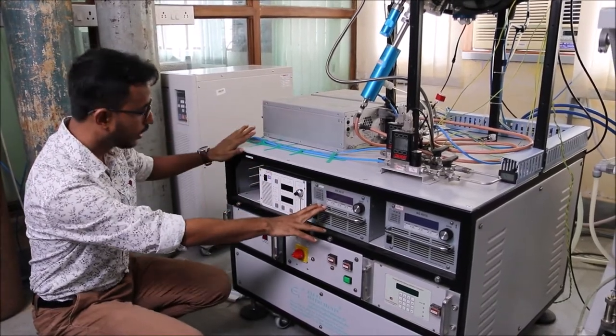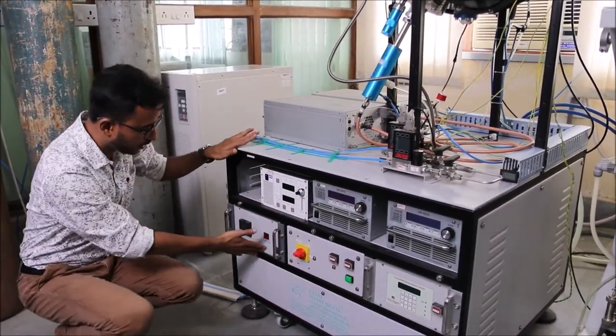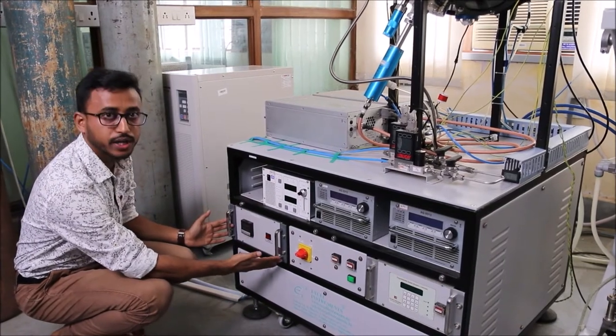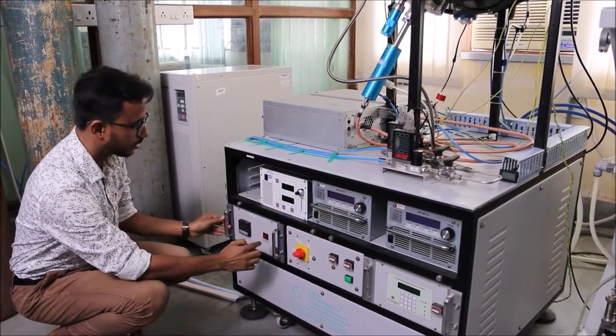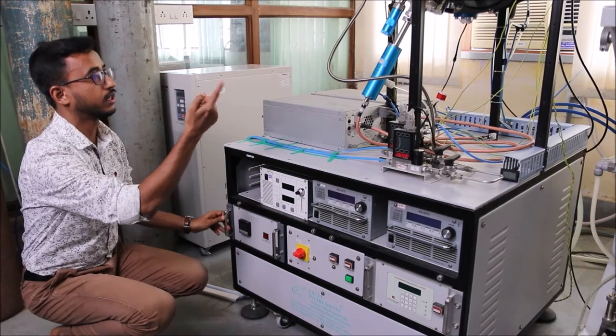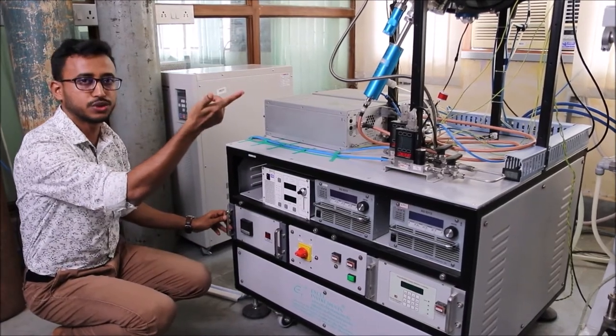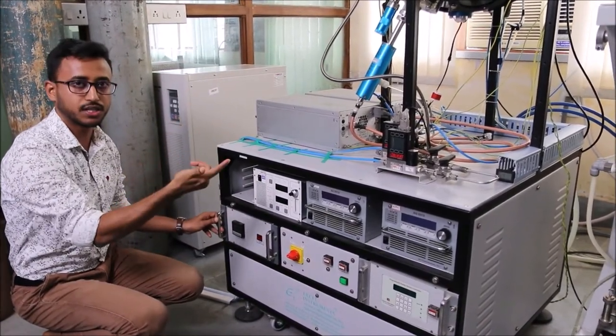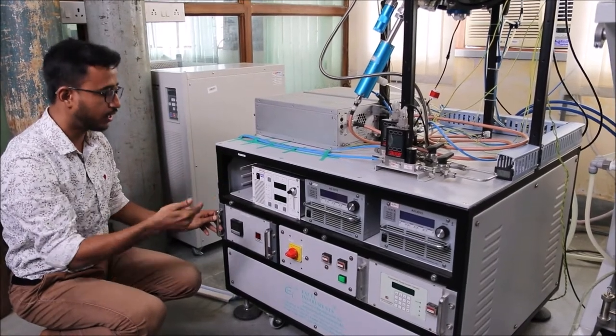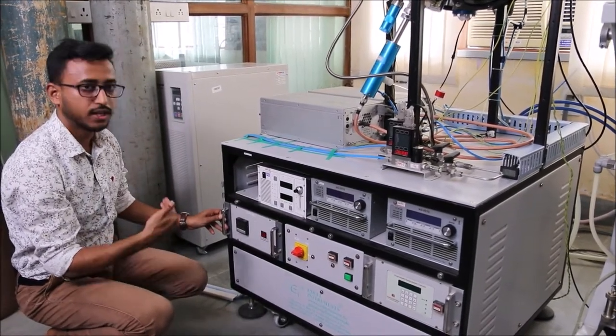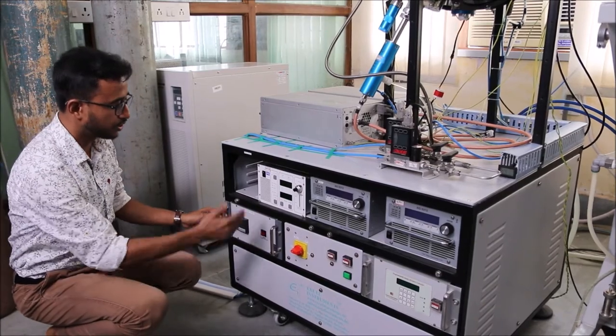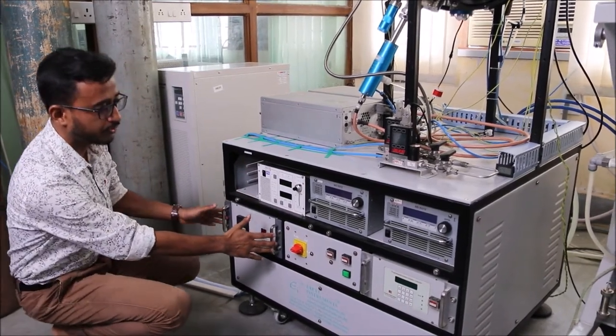And on the bottom of this, this is a temperature controller unit. Our temperature heater coil is connected very close to the substrate, so that while deposition, we can heat up the substrate and grow our film at a desired temperature. So the temperature is controlled by this unit.